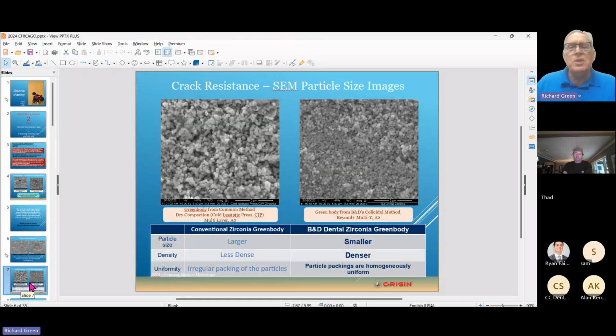So the next one is here. This is showing you just some images of a green state zirconia. This is a CIP zirconia, cold isostatic press, and this is ours on the right. Now, part of the reason why these images look a little bumpy is that after we cut the discs, we had to lightly sandblast the surface to be able to see the individual grains before we took the picture. That's why it looks a little wavy. But you can see that our particles over here are in much greater contact, much more intimate than the cold isostatic press stuff. That means they're going to sinter better.